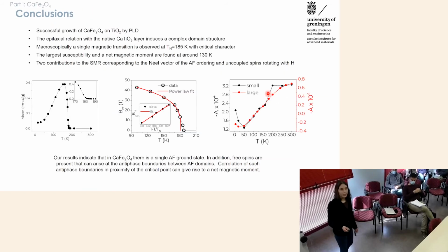And so what we learn is that these non-interacting spins can very well match with what is reported for the spins at the antiphase boundaries of the calcium ferrite. So we can grow thin films of calcium ferrite by means of pulsed laser deposition, and the structure of these films follows epitaxially the structure of the substrate and is mediated by this calcium titanate layer at the interface. And macroscopically, we observe that there is a single magnetic transition. So differently from a single crystal sample, we only have one ground state that orders through a second order critical transition.